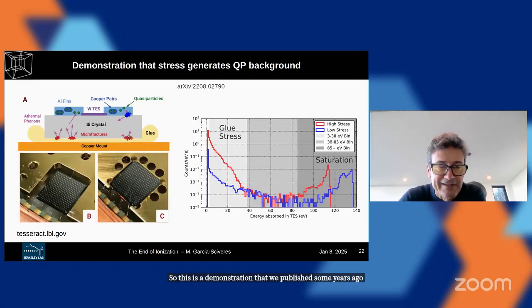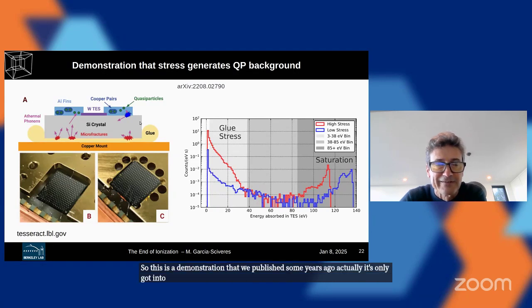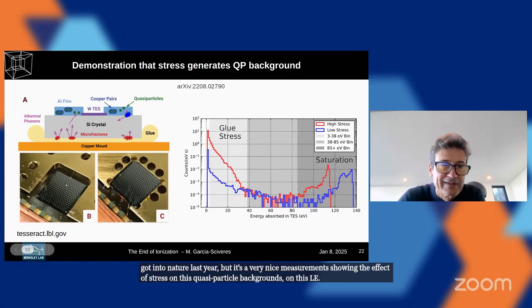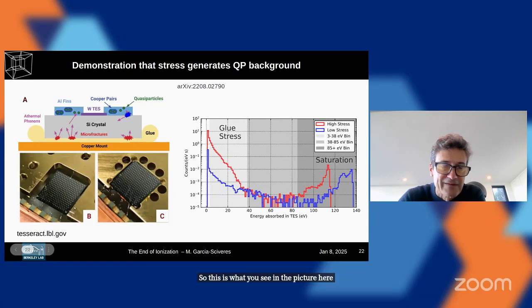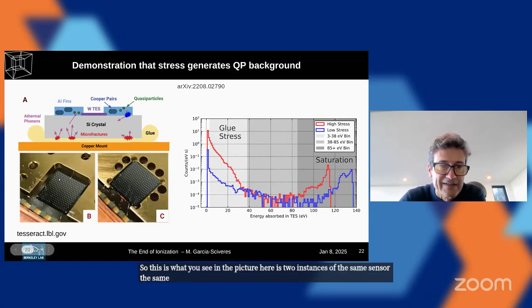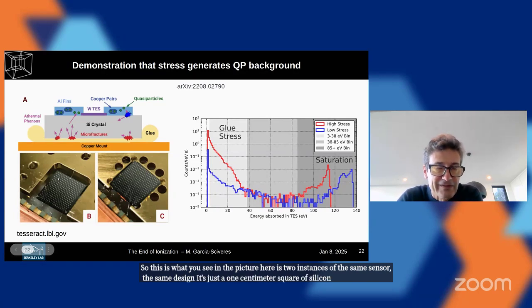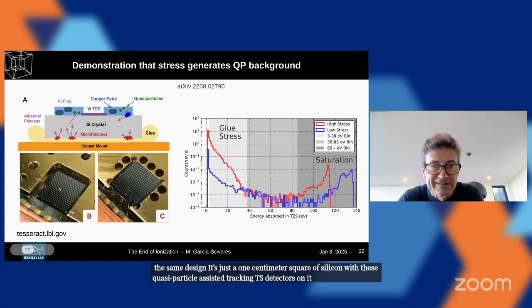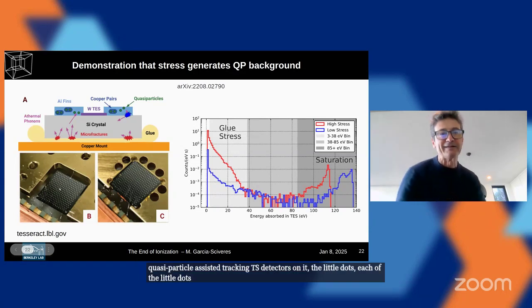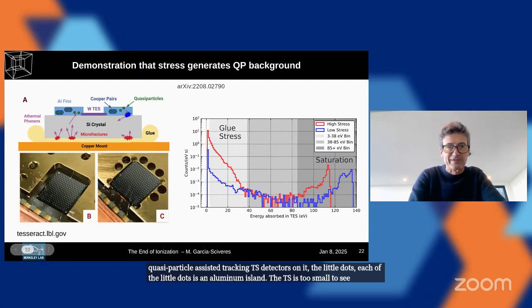So this is a demonstration that we published some years ago. Actually, it only got into Nature last year, but it's a very nice measurement showing the effect of stress on this quasi-particle background, on this LEE. So what you see in the picture here is two instances of the same sensor. It's the same design. It's just a 1 centimeter square of silicon with these quasi-particle assisted trapping TES detectors on it, the little dots. Each of the little dots is an aluminum island. The TES is too small to see, but inside each aluminum island, there's a TES.